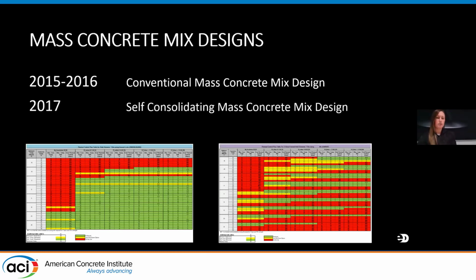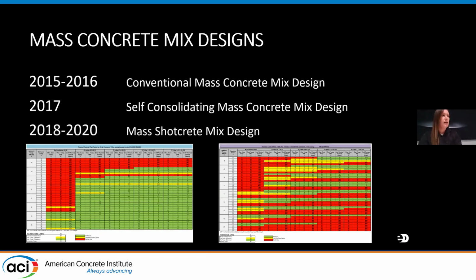And then after a year of construction, the site teams recognized that some of the roof slabs were heavily congested with reinforcement and conduits. So a self-consolidating mass concrete mix needed to be designed as well. This is actually something I'm going to be presenting at the spring 2022 convention. But the same procedure of testing and developing the mix designs was done. And then later on, I guess it was 2018, we realized we needed to shoot some of the walls. Unlike the mixes that were already approved, the Shotcrete mix and the Shotcrete method in general is slightly harder to prove out.